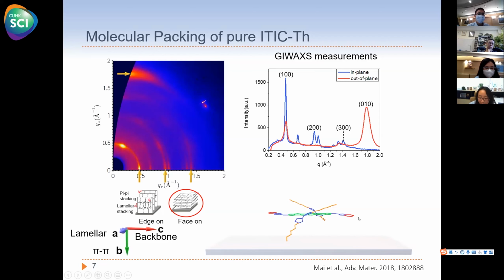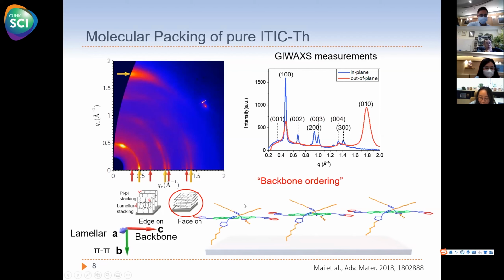Okay? And then in the in-plane direction, we find another group of peaks located at different Q, and they are also up to fourth order. That means there exists another long-range structural order in the in-plane direction. So we guess it is like this: it is the backbone order due to the end group pi-pi stacking, so we can extend the structural order in this direction.